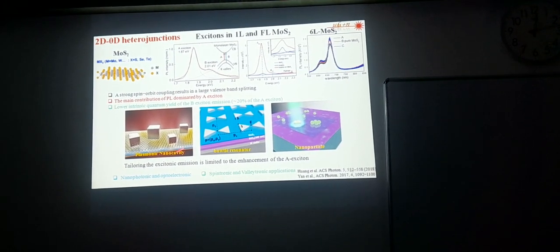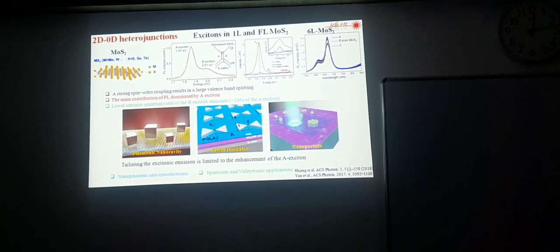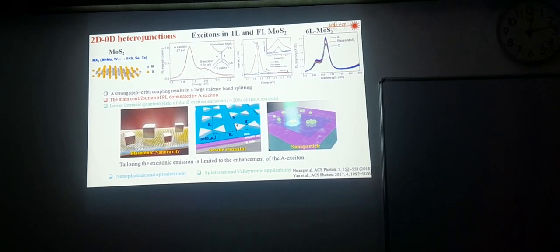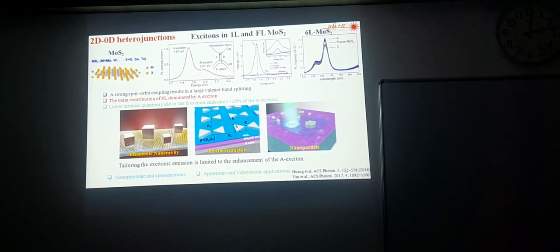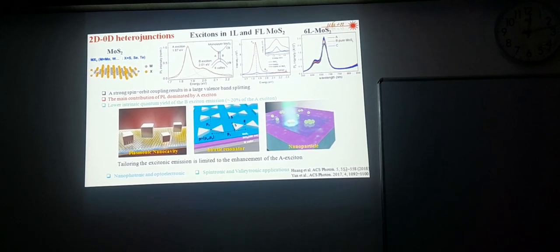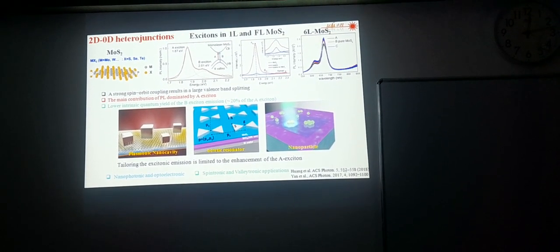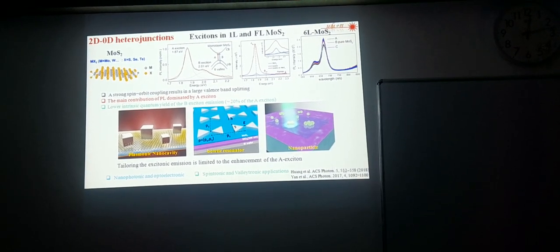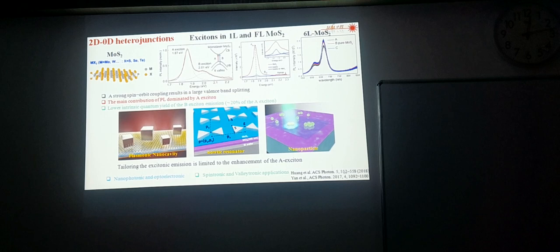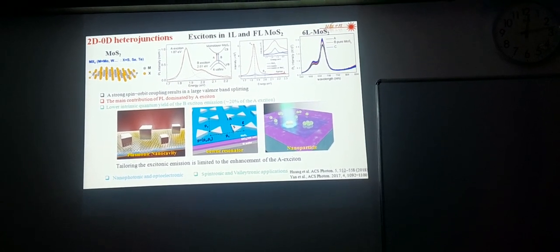There are various methods recently used, but they are very expensive because you have to make a nanoperiodic structure and do some lithography before you fabricate your device. So we thought in a different way. We introduced a glass, phosphate, which is a transparent semiconducting material and well studied. We introduced this 2D material inside this glass matrix, and this glass matrix has some plasmonic nanoparticles, which have a surface plasmon, with positive and negative surface charge. This plasmonic band can resonate with the B exciton. When it is resonant with the B exciton, you can tune the B exciton emission and make it dominate.